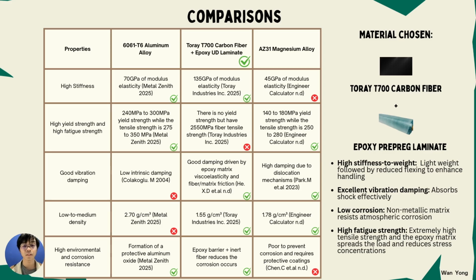Fourthly, density also plays a major role. Aluminum has a density of 2.7 grams per cubic centimeter, and magnesium is lighter at 1.78. But the carbon fiber laminate is the lightest at only 1.55. This gives it a higher stiffness-to-weight and strength-to-weight ratio, making it easier to handle while offering superior structural efficiency.